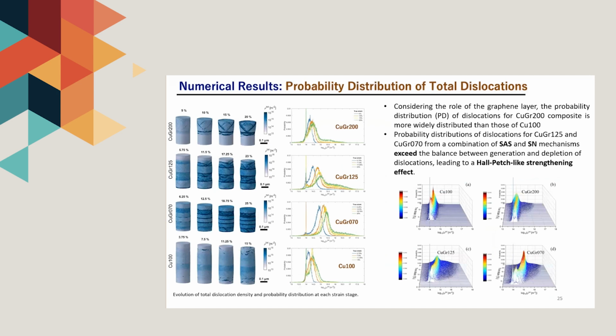The evolution of probability distribution of total dislocation density follows the color sequence of blue, orange, yellow, and green. Simulations for copper graphene composites show more widely distributed probability in the 3D mappings than those of copper 100. Meanwhile, copper graphene composite systems demonstrate a Hall-Petch-like strengthening effect because the combination of single arm source and surface nucleation mechanisms surpasses the balance between generation and depletion of dislocations in the samples.